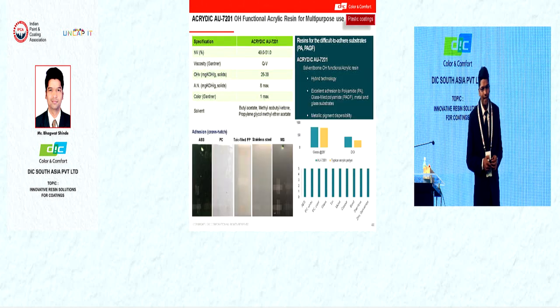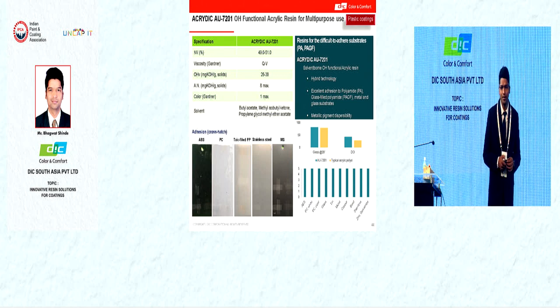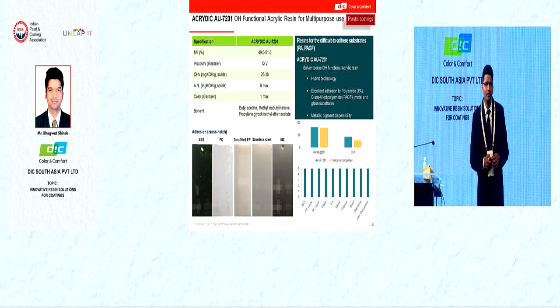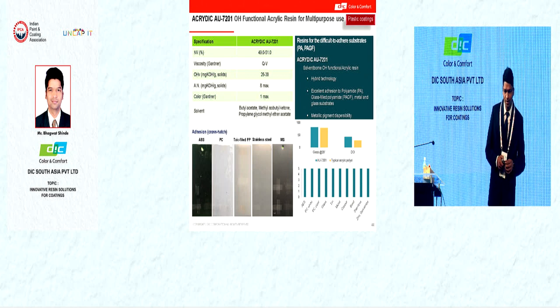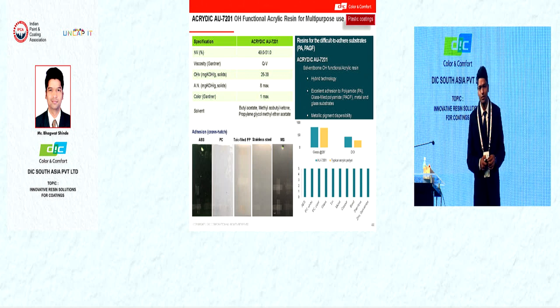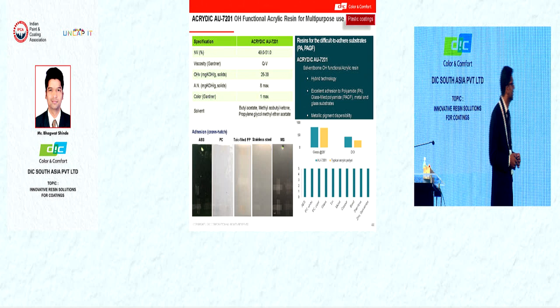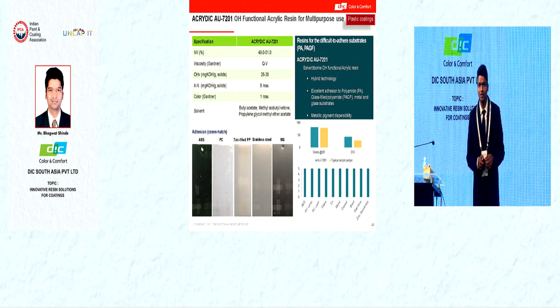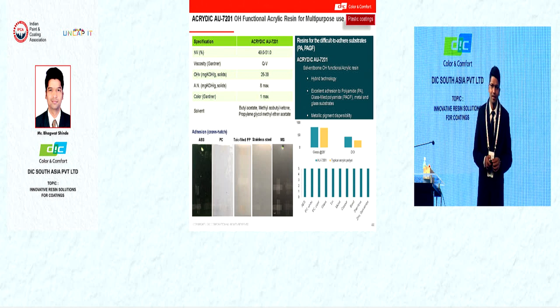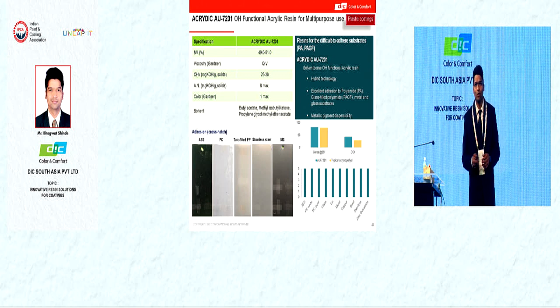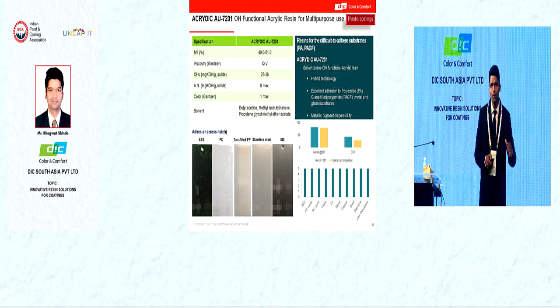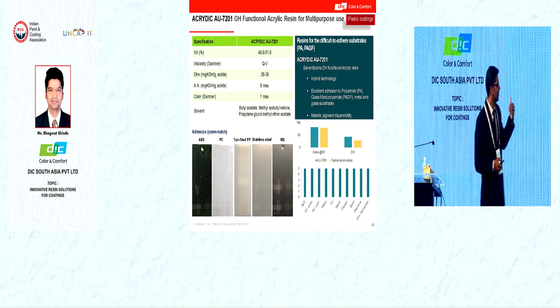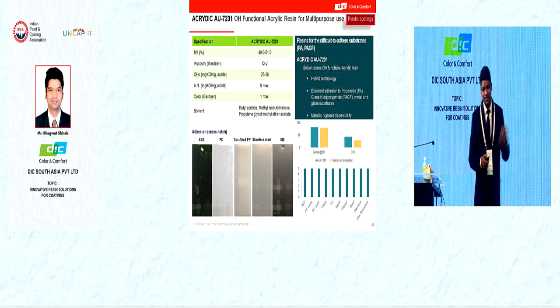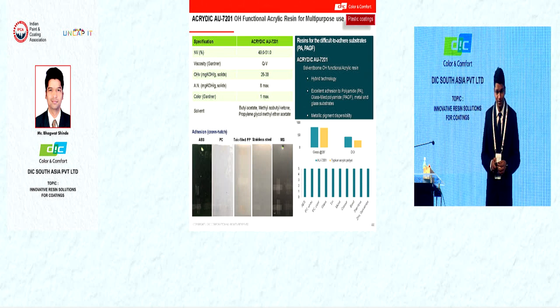The next one is Acrydic AU-7201. This is also a hydroxy functional resin. We recommend it for multi-purpose use. This product is around 50% solids. Also, this product shows good adhesion to substrates which are difficult to get adhesion on, like nylon or glass-filled nylon. So you can use this product directly to get adhesion on such substrates. These products also show a high gloss.